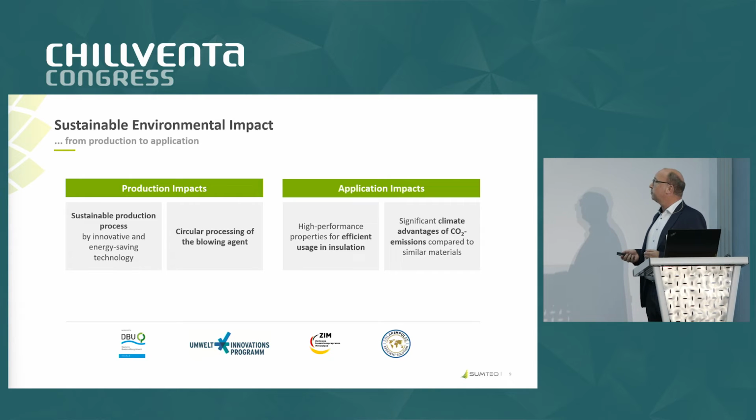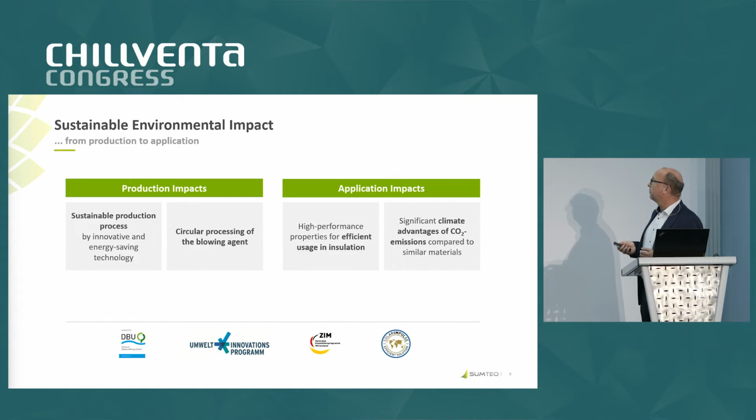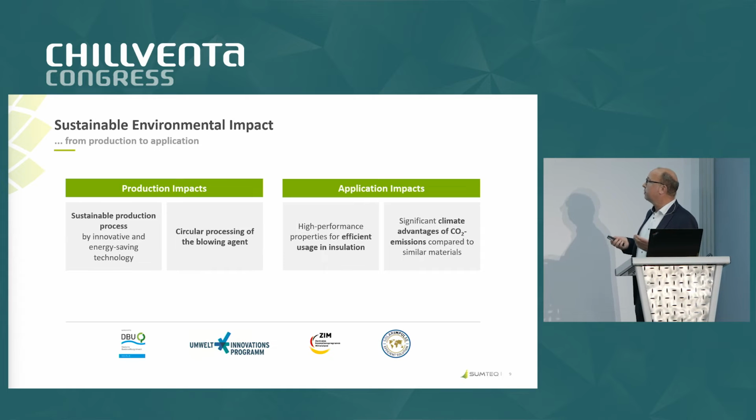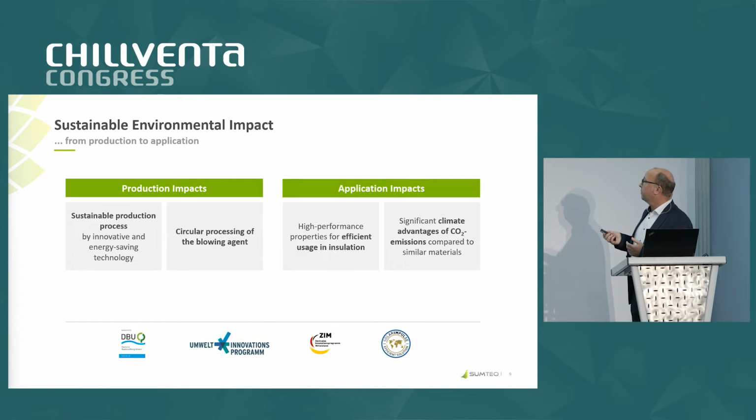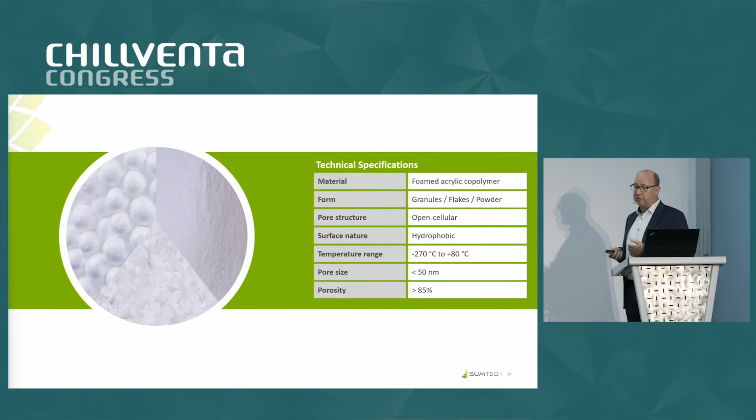Here you can see a little bit about the facts of the foam. It's a foamed acrylic copolymer. Granules, flakes, powder, I said before. The pore structure is open cellular and very homogeneous. The pores, we say, are below 50 nanometers.